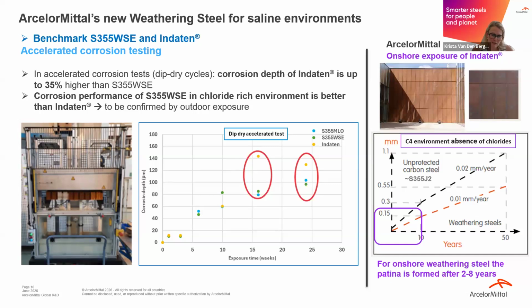So we see in this accelerated corrosion test, where we accelerate the humid-dry cycles to see a result faster than in the real outdoor, that after some weeks of exposure in this test, we really have a lower corrosion depth for the saline-resistant weathering steel compared to the standard Indaten material. So this is a promising result, where the saline-resistant weathering steel can be a material close to the seaside where the current Indaten cannot be used.